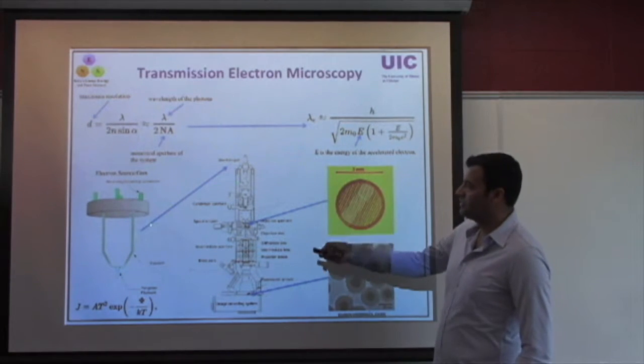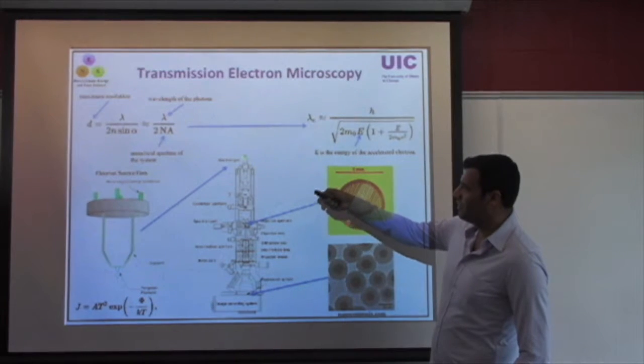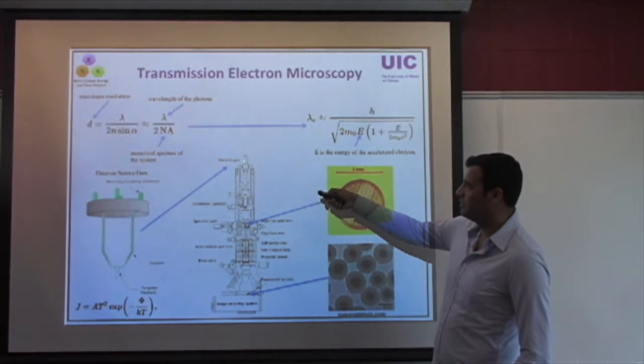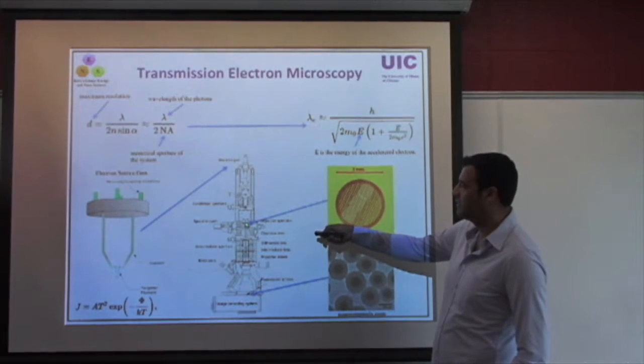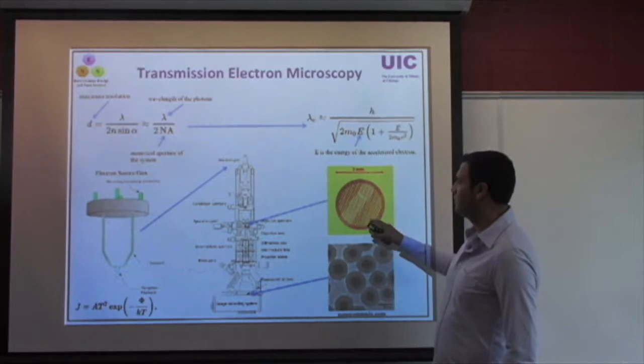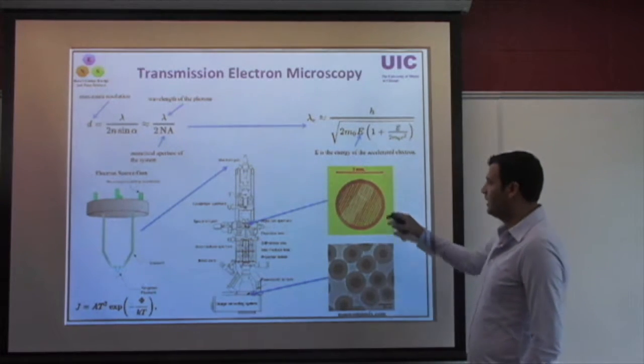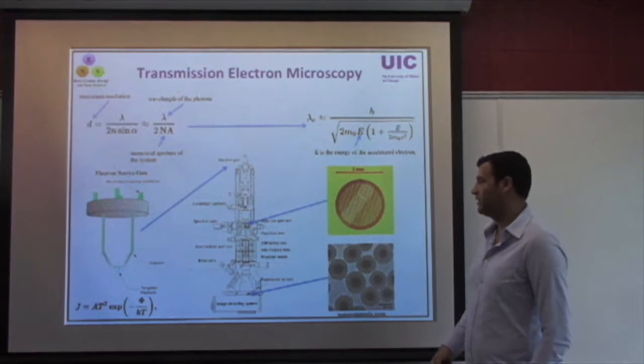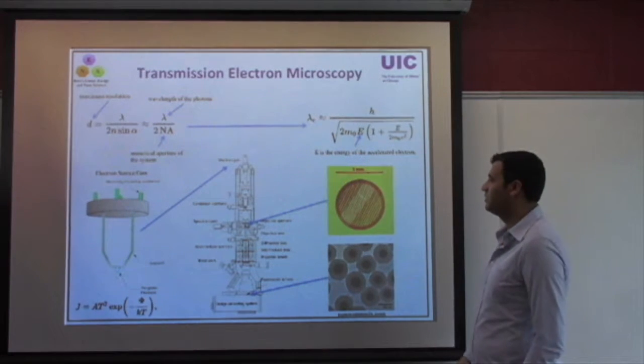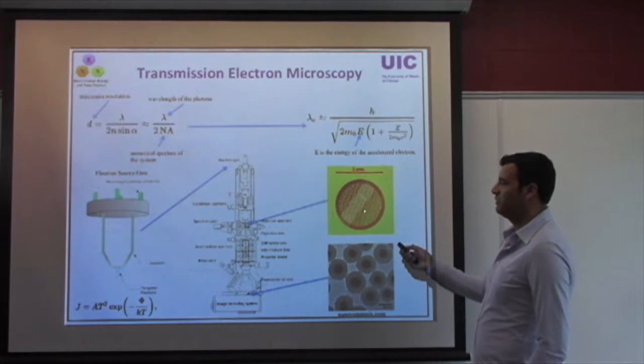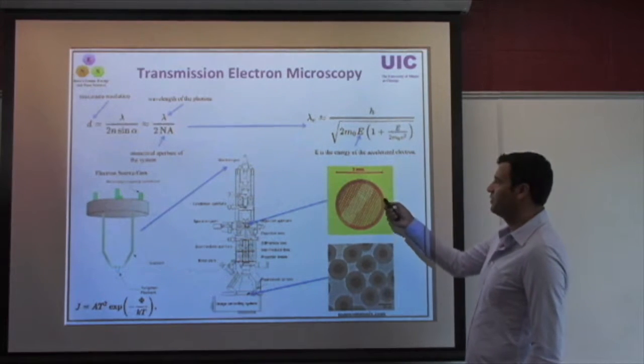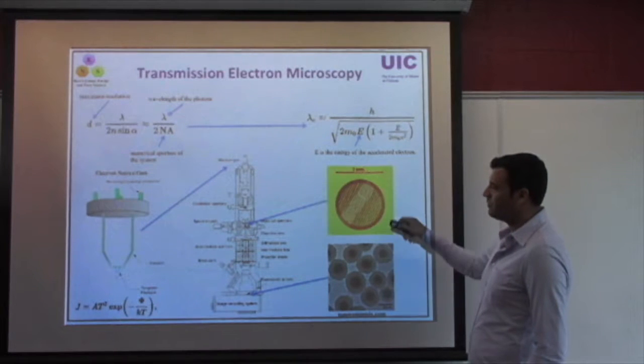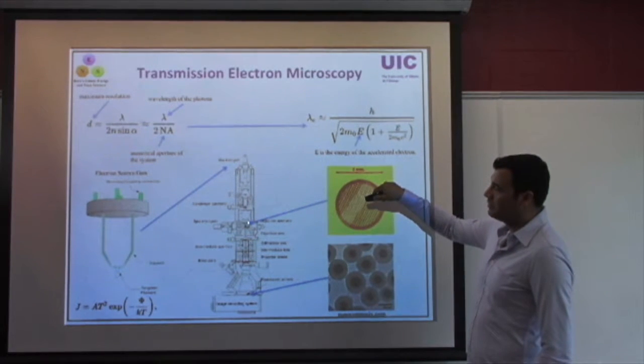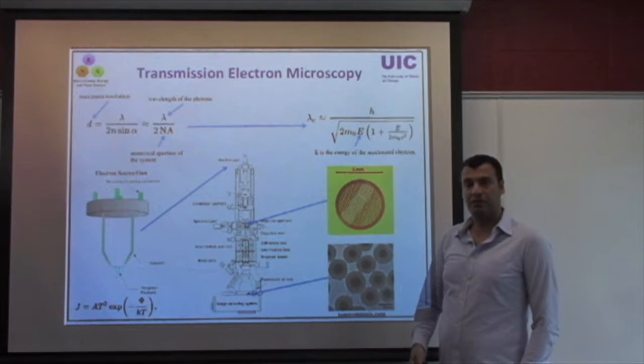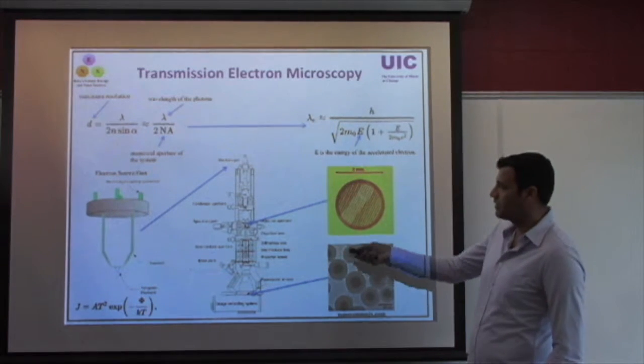This gun is usually incorporated at the very top of our electron beam systems or TEMs, and electron beams shoot over the samples that are typically deposited on a grid. Your sample could be flakes, particles, or thin films, a variety of forms, which you can deposit on grids on the order of 3 millimeters. And the electron beam transmits through the sample. That's where the name transmission electron microscopy comes from.